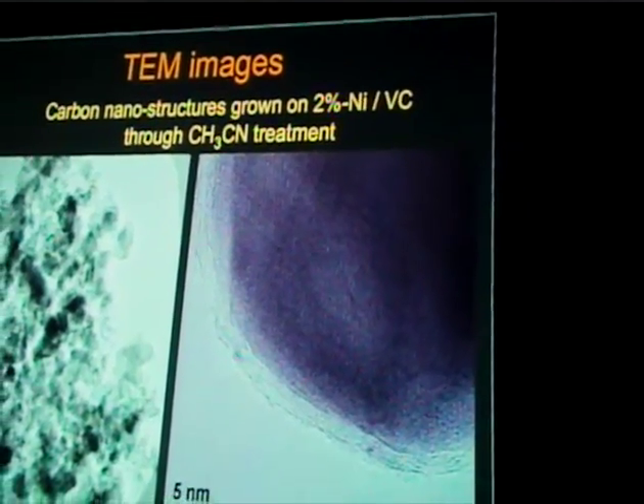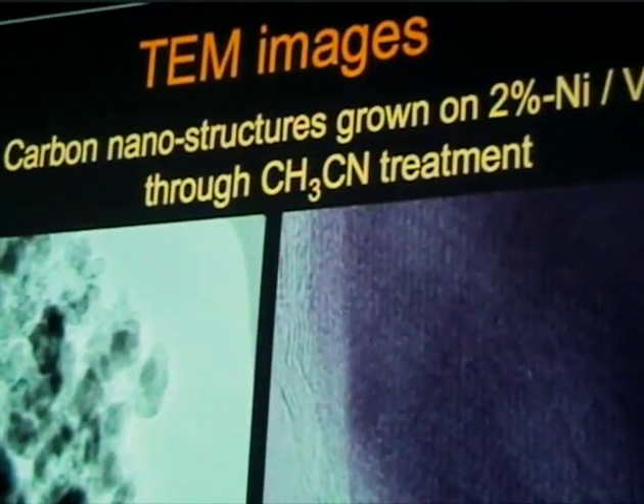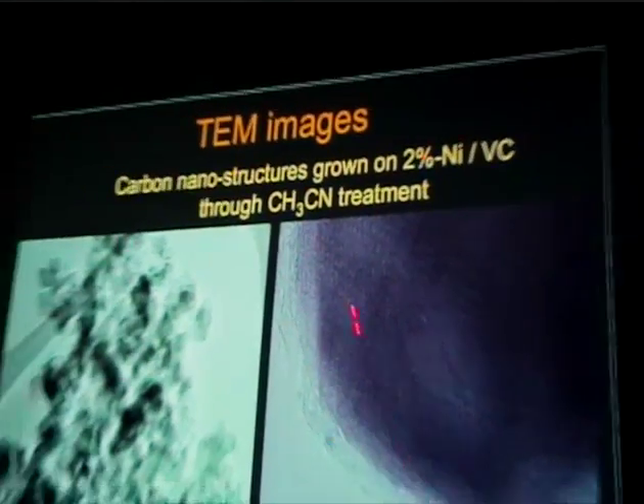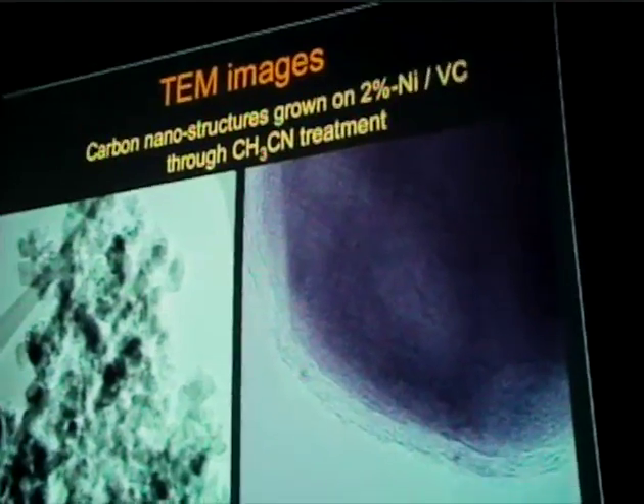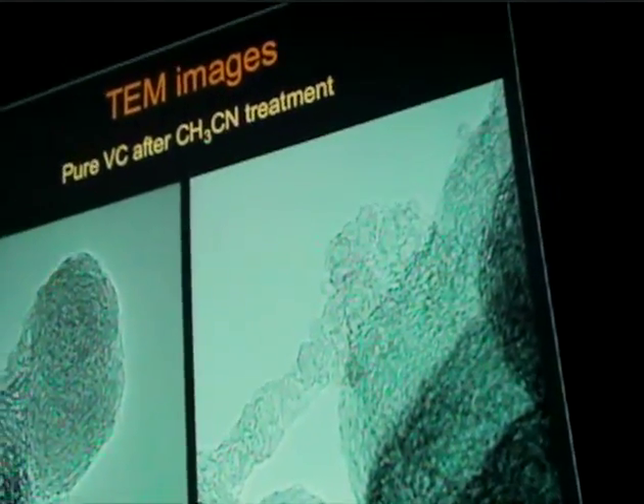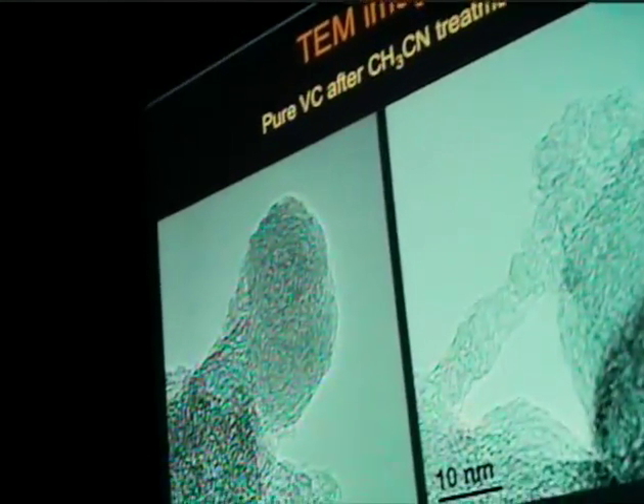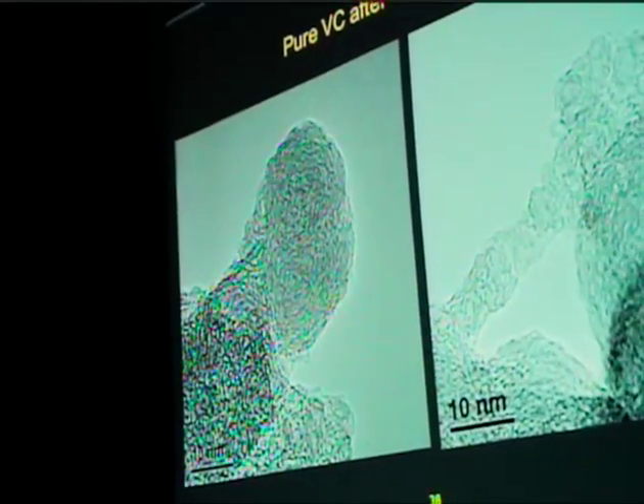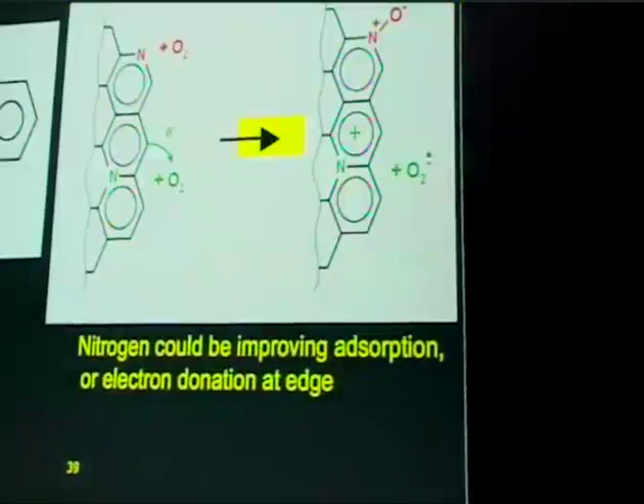If we look at structures which are grown on nickel-containing Vulcan carbon, we don't really see the fibers. We have mostly these onion-type materials with very little edge plane exposure. And this is pure Vulcan carbon after acetonitrile treatment. Again, as you can see, we have mostly these nano onions.